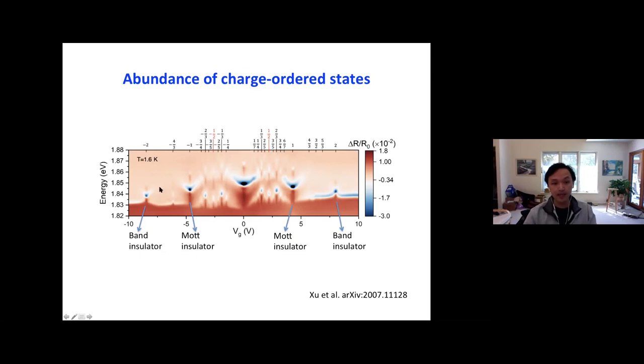You can see the band insulating state as well as the Mott insulating state, as we discussed before. But in addition, you can see a bunch of fractional states between filling factor zero and one, as well as between filling factor one and two. Typically these fractional states are much more obvious between filling factor zero and one than between one and two. What we believe is that the kinetic energy of the electron is significantly increased between filling factor one and two. With reduced kinetic energy between zero and one, the system is basically like a classical electron gas. And these are Wigner crystal states that try to minimize the long range Coulomb repulsion.